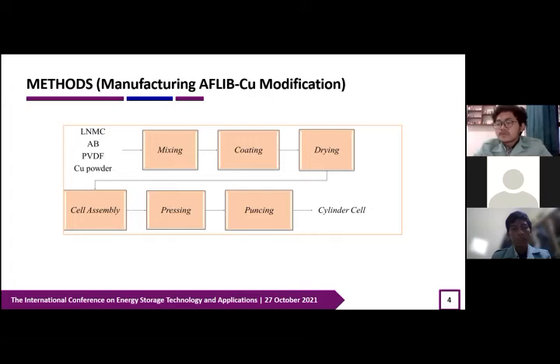The dried battery film and material will be processed to form a cylinder cell battery. Battery film is pressed using a hot rolling machine and molded into a round shape. Cylinder cells were made by cutting the dried battery film with a size of 10.5 centimeter long and 5.6 centimeter as cathode film, while the anode film material was cut with a size of 13 centimeters. After that, the battery component plates are rolled together with the separator